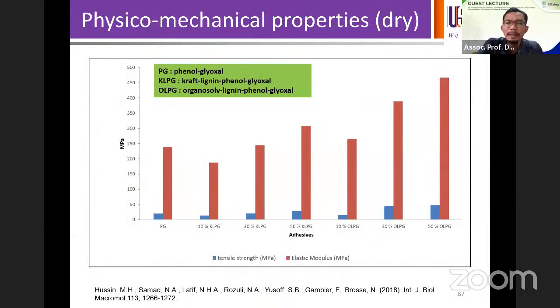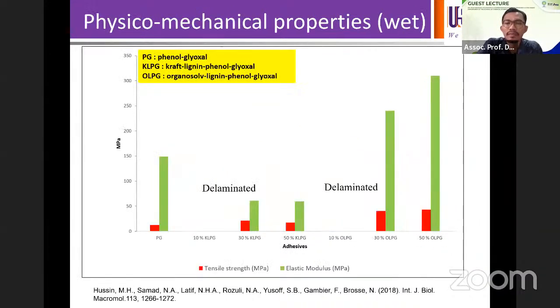And finally, we also did the mechanical properties of the panels. As I mentioned, we did different percentages of lignin substitution. In this case, the panel is in a dry condition. We obtain a very high tensile strength for 50% lignin substitution as compared to kraft lignin. Meanwhile, we also did a wet condition where the panel is soaked in boiling water. This is to see whether the adhesive or the panel will delaminate or not. At the lower percentage of lignin substitution, the panel delaminated, but at the higher lignin substitution, for example, 50% organosolv lignin adhesive, it still gives higher tensile strength as compared to the control sample.